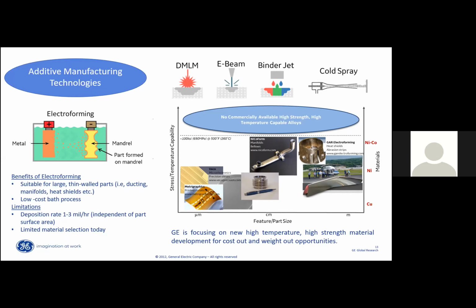So at GE, I have led projects since 2016. We are working on developing nickel-based super alloys for temperature capabilities greater than 500 F and up to 1200 F. And we are developing these materials for 1 mil thick products, right? That's important because typically in an electrodeposition process, your residual stresses will start to increase with your thickness, and especially on a complex part with all those twists and turns.